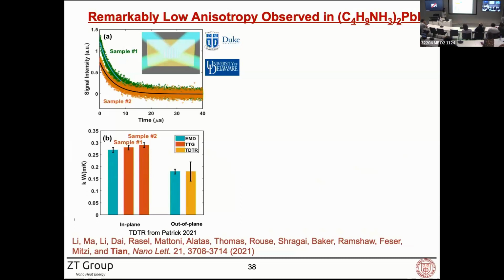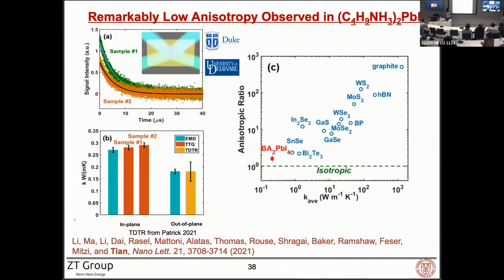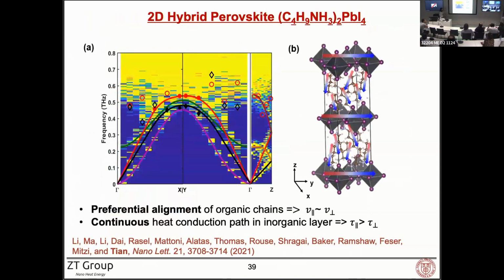Now, to put this in context with other layered structures, we plotted the anisotropic ratio versus the thermal conductivity of the 2D hybrid with other layered material. So we can see it really go towards the lower left corner, meaning the thermal conductivity is ultra low and it's pretty much approaching the isotropic limit. Now, to understand this better, we also did the inelastic X-ray scattering. Those markers are from our X-ray. And we did the MD simulation to map out the dispersion.